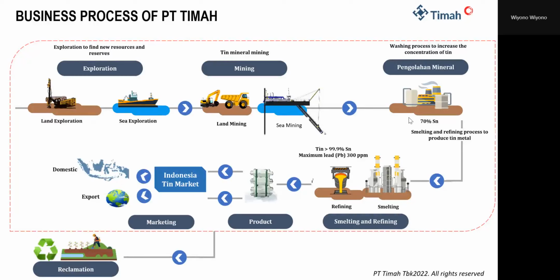Besides the grade of tin concentrate, we also consider impurities, because if we smelt the tin concentrate far below 70, it means we will get a lot of impurities. It will be difficult to refine the impurities if we have a lot of impurities from the low grade tin concentrate. So after we increase the grade of tin concentrate at the mineral processing plant, we will bring it into the smelter.